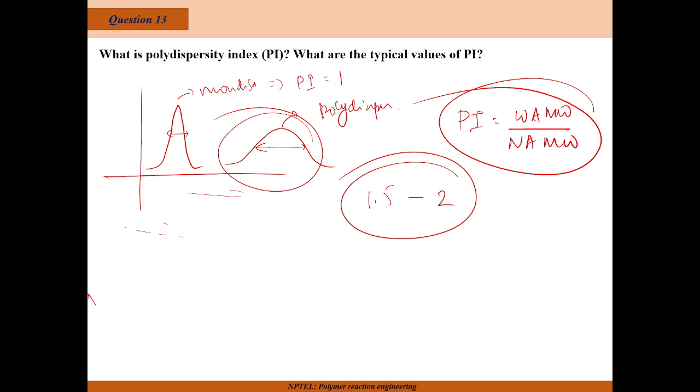Practically, both will have different applications. With polydispersed polymers, if I am looking for control of a property, say I am converting this polymer into a composite matrix in which I add some fillers, I can tailor the properties to my requirement. It gives me the flexibility to tailor the properties. Whereas with monodispersed polymers, generally the molecular weight or monodispersity is fixed, so I cannot play too much on this.